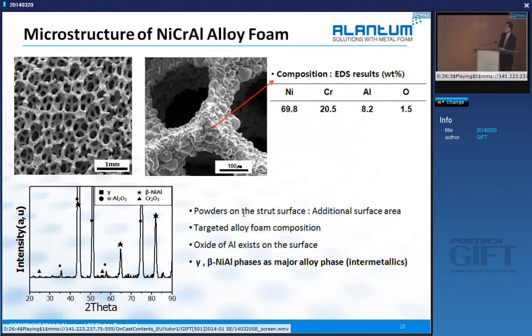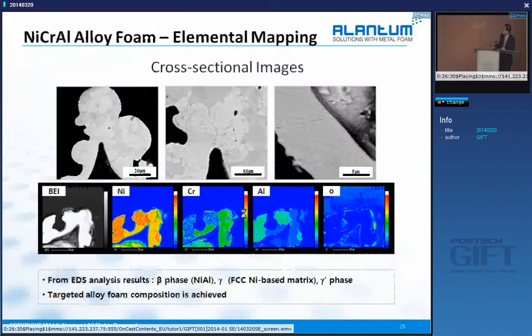Then later we confirmed, or verified, what the compositional distribution really is here. So eventually roughly 20% chromium, and about 10% aluminum. And then X-ray diffraction also showed that we contained gamma and beta nickel aluminide phases as intermetallics in the alloy. Elemental mapping of the cross-sectional images also shows the aluminum, nickel, beta phase and other stuff. As you see here, like a beta phase and a gamma phase or a gamma prime phase.